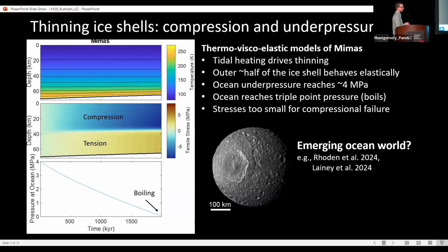So these are similar models, but now we're supplying an excess tidal heating that drives ice shell thinning. The top panel shows temperature and the evolving ice shell thickness. The middle panel shows the deviatoric tensile stresses. You can see that near the surface, there are increasingly compressive stresses, and the basal part of the ice shell is in a state of tension.